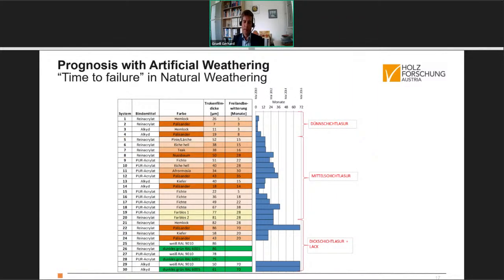We put the same systems in a 7 years test or 8 years test of outdoor weathering. And again, we figured out the time to failure in outdoor weathering expressed in months. Again, 4 systems did not reach the limit states over 8 years of natural weathering. And again, these were opaque systems, and 3 of them the same opaque systems as we've seen earlier in the artificial weathering test. So in principle, for the opaque systems, which were very durable, the artificial weathering tests selected the best ones out of these systems.